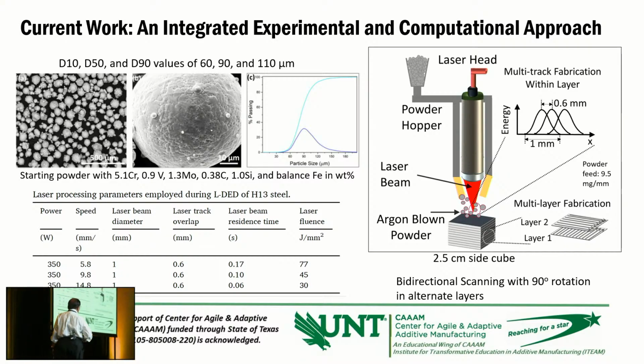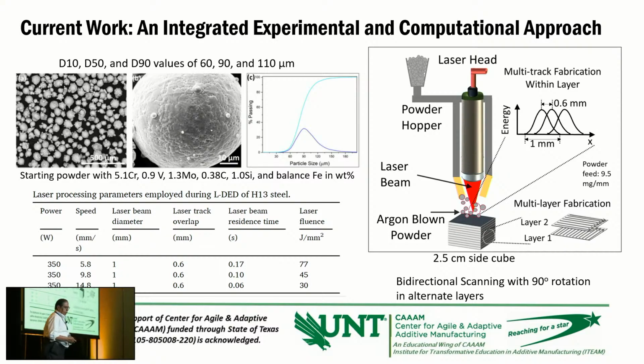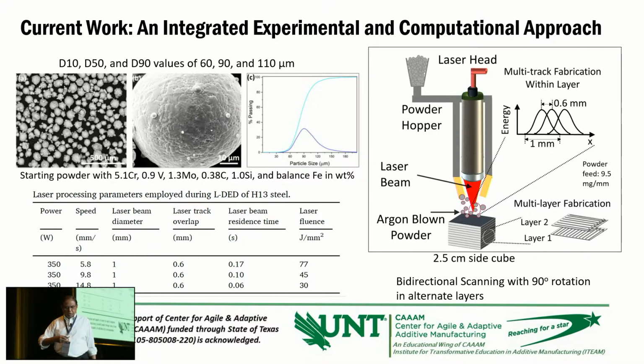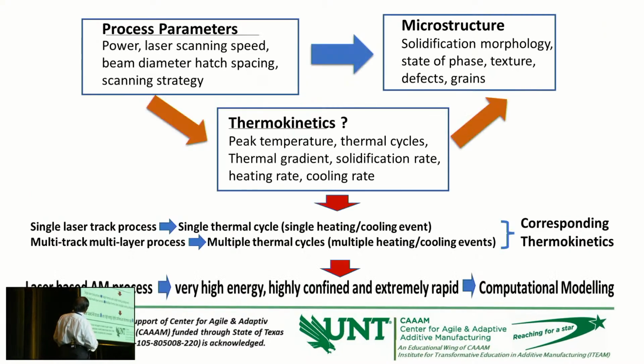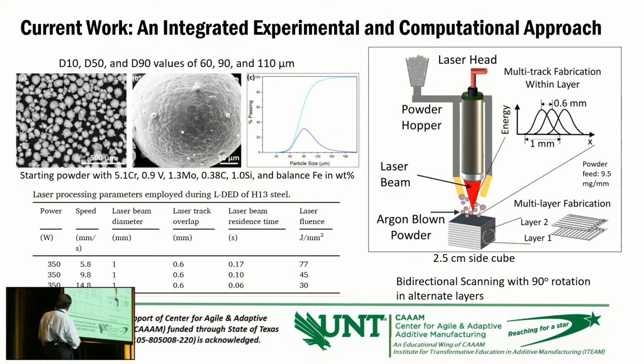Then your properties are very dependent on the elongated grains. They are very poor in creep and fatigue response, as far as that is concerned. So you want equiaxed grains, and grains which are oriented in different directions, to get uniform properties in the material. To avoid that situation, there are various scanning strategies, which I mentioned earlier in this slide. One is you go in the same direction, which produces the elongated grain.